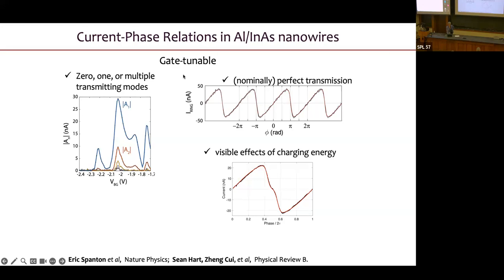Just to summarize on the current phase relations of the aluminum indium arsenide nanowires, we found that they're gate tunable. We can tune it into where there's a single transmitting mode. We found a region where we can tune it into something that's consistent with perfect transmission through a single mode. And we also found that we can see visible effects of states with charging energy, which I initially thought was some evidence of disorder in the wire. But after Andrey and Roman did their calculations, I realized that it's exactly what you'd expect for a wire of this shape because of the finite energy levels inside the wire.